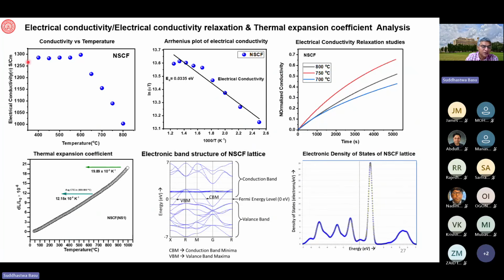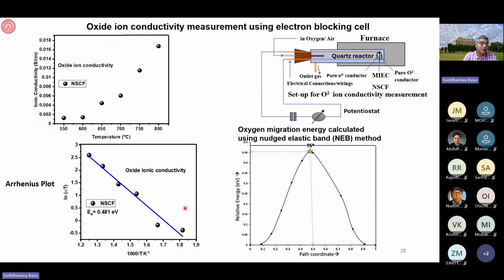And now we are showing NSCF conductivity. You can see very high electronic conductivity. Arrhenius plot, electrical conductivity relaxation, we are trying to show. And here we're showing the density of states calculation. From there, we can show you the valence band and conduction band. And these bands are close to the Fermi level. They are overlapping. And that is the reason you have very good electronic conductivity in the NSCF material. That is the reason you have such a nice overlap of CBM and VBM, the valence band and the conduction band that we have shown.